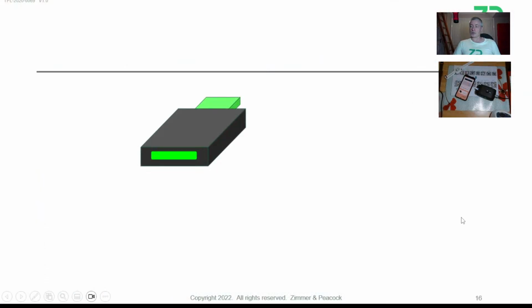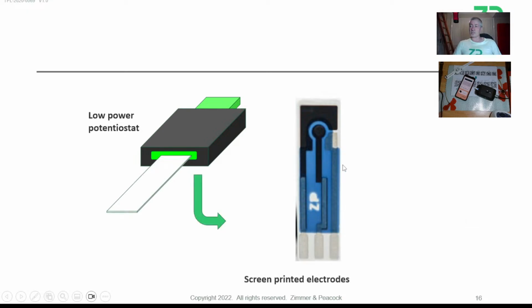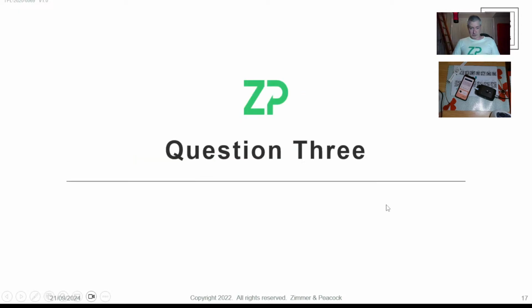It's easy enough to drop cast onto these circular electrodes. It's probably worth saying as well that we've really worked hard on the design of this screen printed electrode. Some of the modern potentiostats that you can find on the market actually have a problem with compliance voltage. Everything's become very low power and USB-C driven. And the problem that they're not telling you is, in fact, that they have a problem with compliance voltage. But this particular screen printed electrode is really good, A, for being able to functionalize on that working electrode, but also it's got a very good counter electrode, which really helps with the compliance voltage.